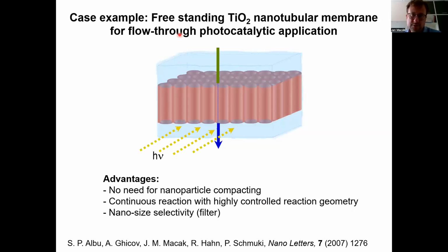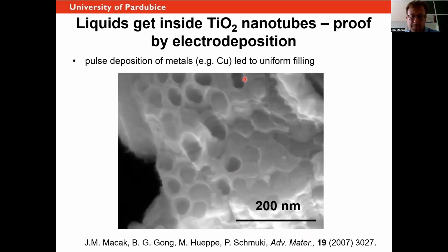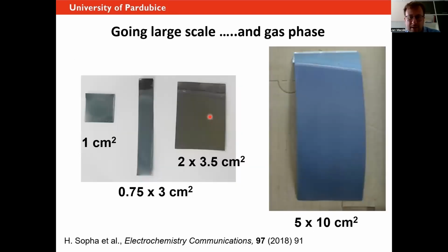It is also possible to use the tubes, when you do the etching and you open them, as a flow-through membrane, right? So you can actually have interesting flow-through applications, and we showed this in this pioneering paper. I was always asking myself if the tubes can get wet inside, and if they really do get wet. And I can tell you that we have some proofs for it, because we have done some electrodeposition, and we always got the material growing inside the tube. So this means that the tubes are really wetted. So that's good.